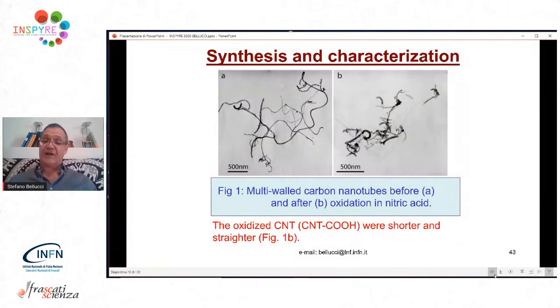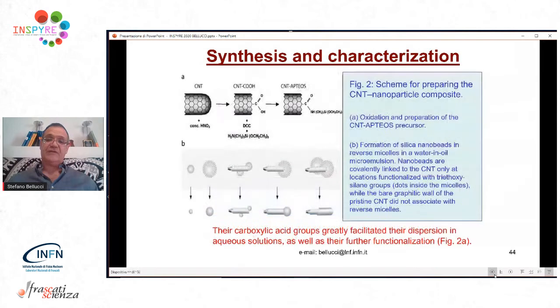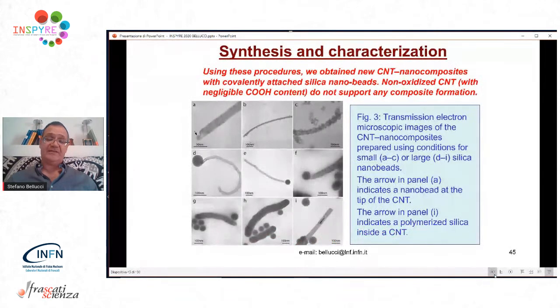The oxidation will put a lot of carboxylic COOH groups on the surface of the multi-walled nanotube, and we will use these groups as a docking, as an attachment for a new, very complex molecule. It's obtained by a precursor in a complicated but standard technique of growing nanoparticles in a micelle. The micelle is actually reverse: it is obtained not in oil in water, but in a water in oil microemulsion. And inside these micelles, we can grow with a predefined size a nanoparticle of silica, chemically bonded to the carbon nanotube site where the defects are.